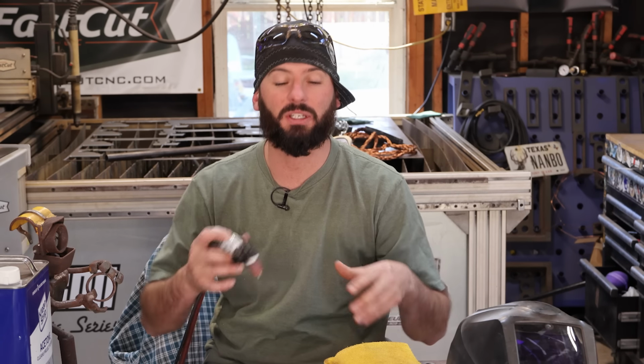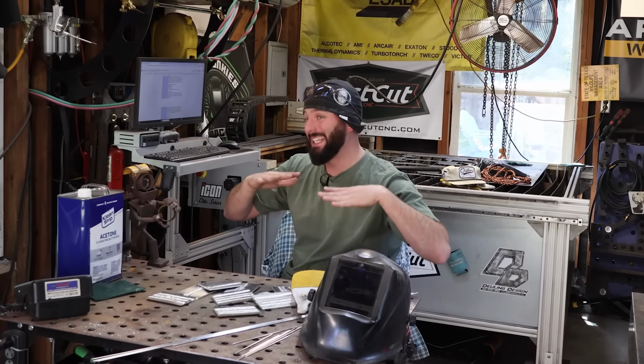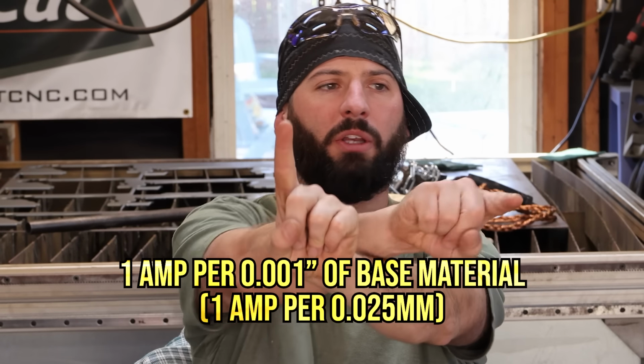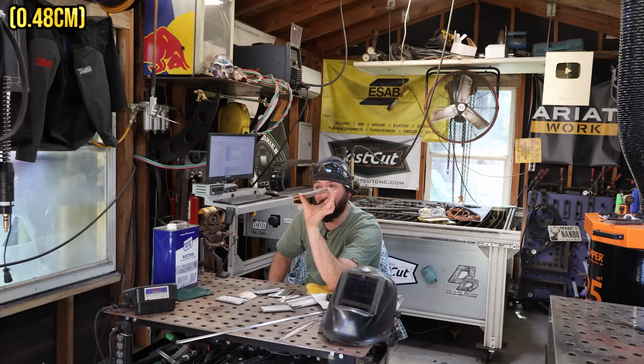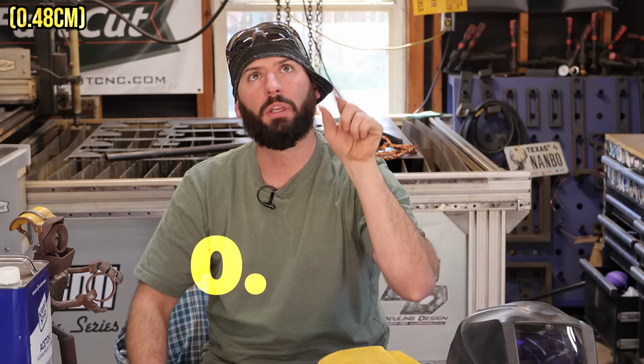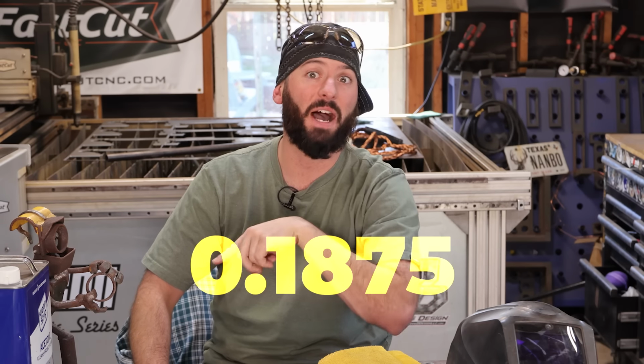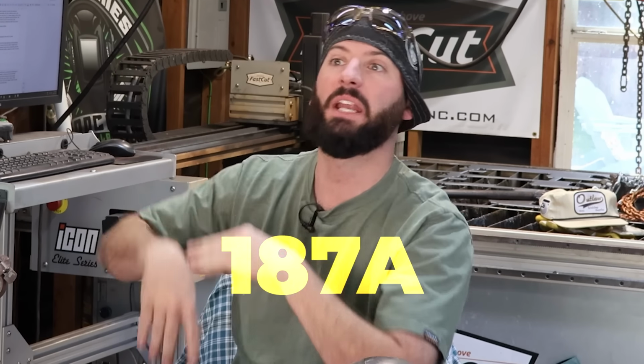But after you get started for a little bit, that aluminum starts to get hot, and when it's hot, all of a sudden it starts to sink and fall out. That's where we got to find that balance. They say the rule of thumb is you get 1 amp per 1 thou of base metal thickness. So I've got 3/16 plate right here. That's 0.1875. We're looking at 187 amps right there, which is a lot of beans.